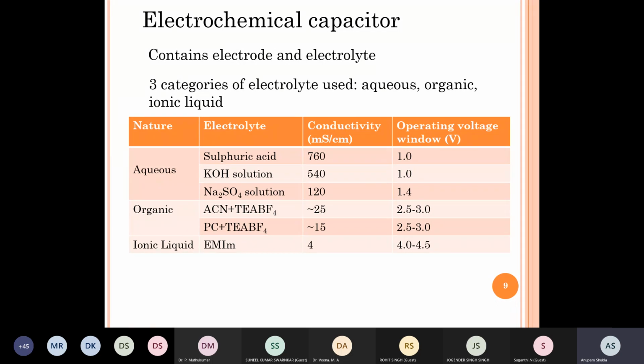Of course, there is another one which is mostly in the laboratory, called ionic liquid. These are mostly imidazolium salts, and they have very poor conductivity. But they provide a very high voltage window when we compare with other liquid electrolytes, 4 to 4.5 volts. Principally, they are still confined to research. Unless something can be done about their conductivity, they will remain in the research labs. Of course, there is another problem associated with ionic liquids, which is their hazardous nature. They are much more environmentally hazardous than the other electrolytes.